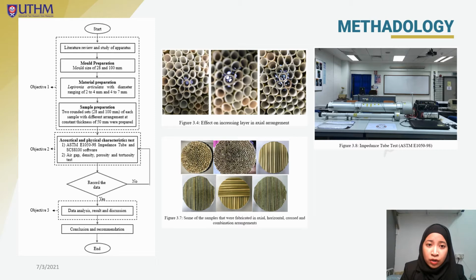For the horizontal and cross configurations, we are using the same method as the previous study. Lastly, in the combination configuration, 2 types of combination were used. The first is a combination of horizontal and axial configuration, where several layers are stacked in the horizontal direction at both ends until the thickness is 50 mm. This procedure is similar in preparing the combination of cross and axial configuration, but each layer was positioned perpendicular to one another at both ends until it reached the constant thickness of 50 mm. In the combination configuration, the axial stack of 25 mm was placed in the center before the horizontal and cross were arranged at both ends.